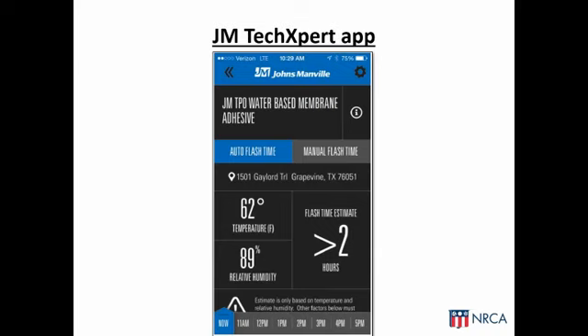The application basically goes out to the internet and picks off the address or the specific location based on your GPS coordinates, and it goes out to the weather sites and gets a temperature and relative humidity value. And then in the background, the app is actually providing a flash time estimate of how long that water-based adhesive is going to take to flash off. And as you can see, in Grapevine, Texas, when it's 62 degrees Fahrenheit and 89% relative humidity, which is relatively high for that time of year, Manville is saying that it's going to take over 2 hours for that water-based adhesive to flash. And that number will vary based on temperature and relative humidity.